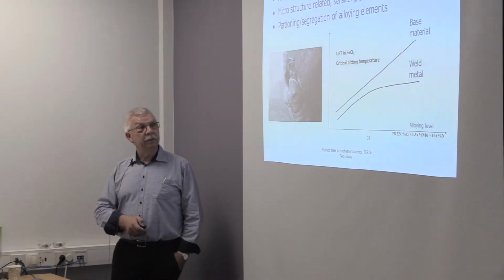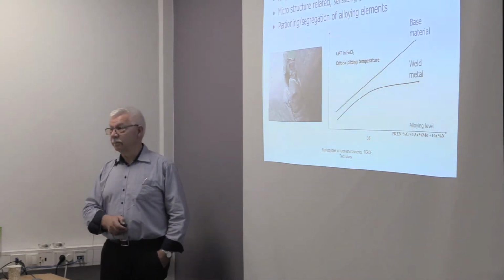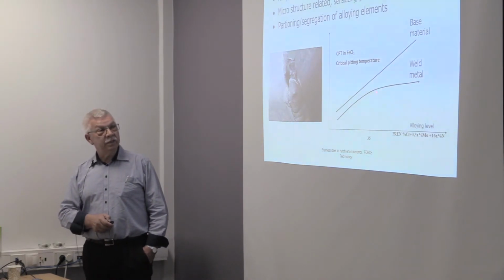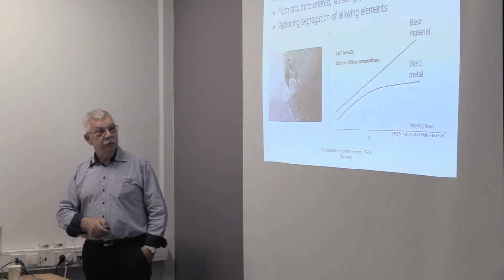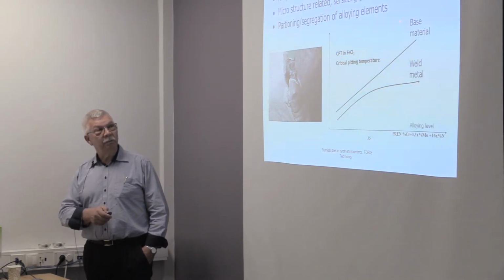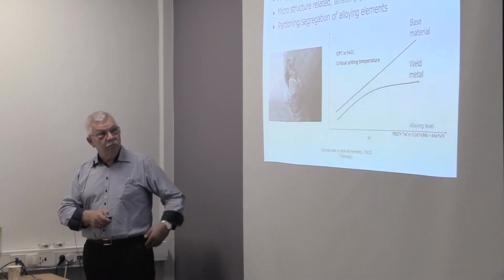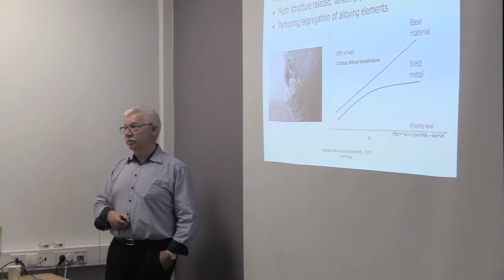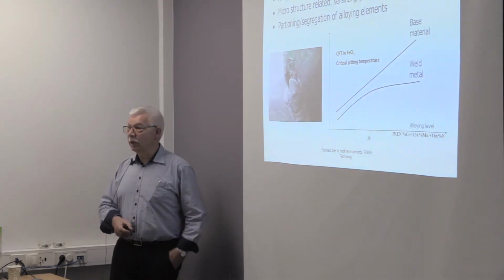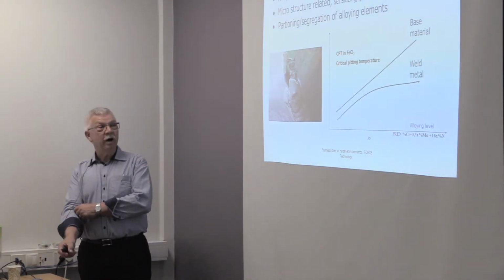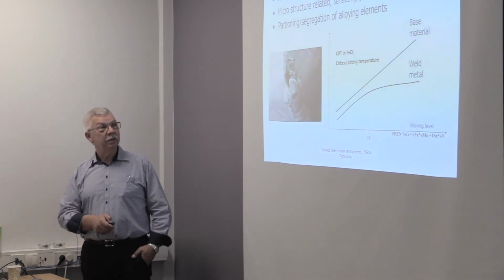And what can we do then? We can add filler material. And the 6% molybdenum steel, the 254 SMO, which is approximately here, will need to be welded with a material up here in order to have the weld metal being dragged up to meet the base material. So in fact, it's welded with an Inconel 625 filler material to meet the base material resistance.